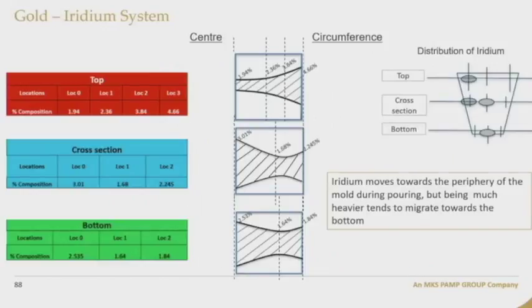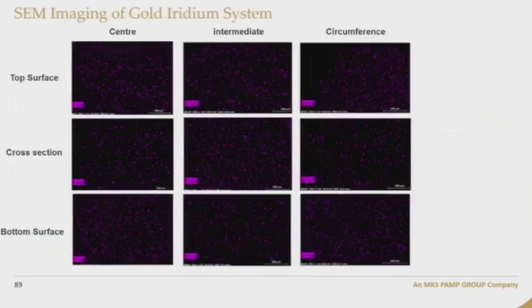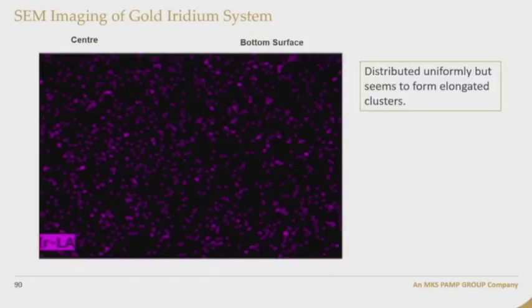We see that iridium moves towards the periphery of the mold in the top surface. It is also found at the cross section, but it settles more at the bottom surface. So iridium moves towards the periphery of the mold during pouring, but being much heavier, tends to migrate towards the bottom. We also did the imaging from the scanning electron microscope, and what we can see is it is distributed uniformly in the melt, but it seems to form elongated clusters.